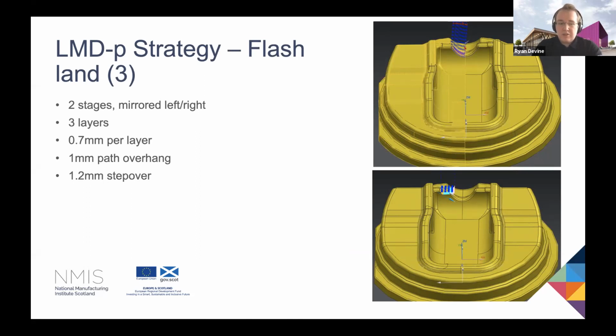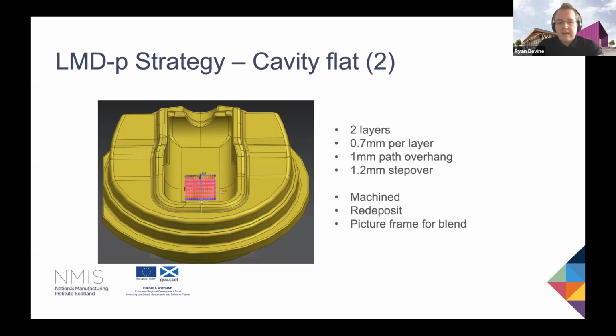We also had a similar parameter set to what we used in Flashland 1 and 4, with 3 layers, 0.7 millimeters per layer, and the same overhang and step over. For the cavity flat area, we only then required 2 layers because it was a shallower cutout initially, same layer height and overhang step over.